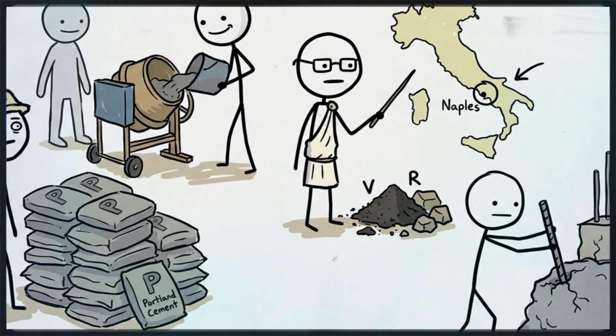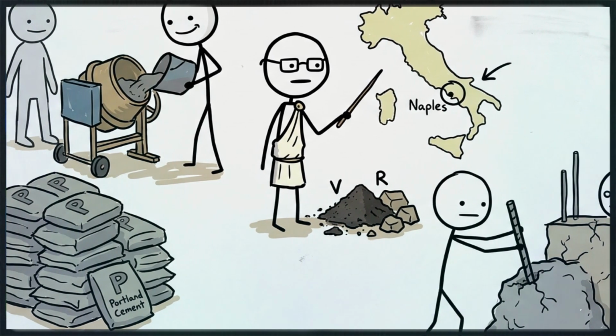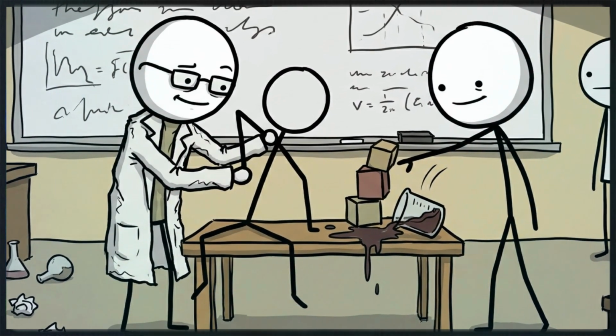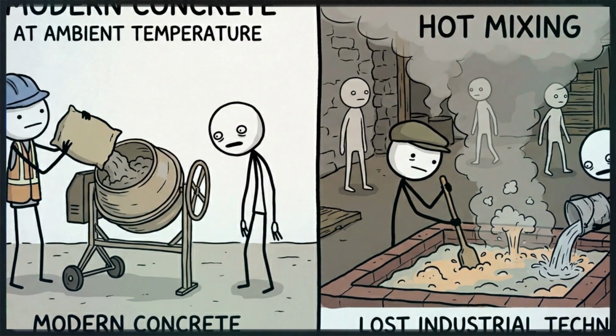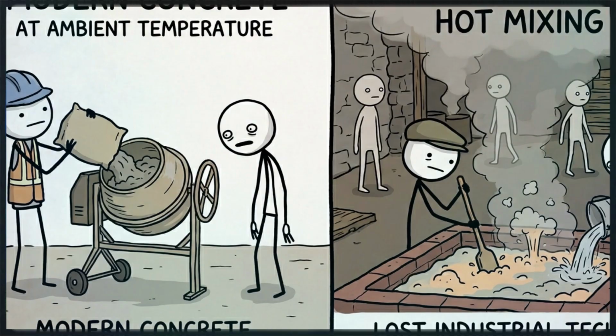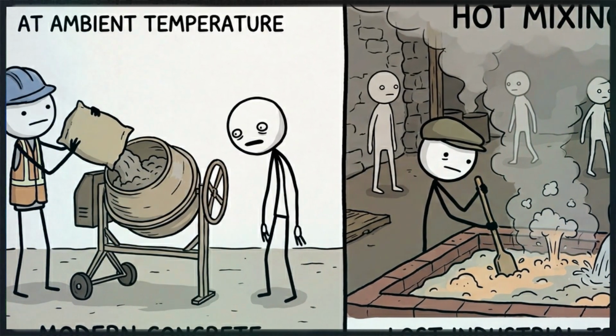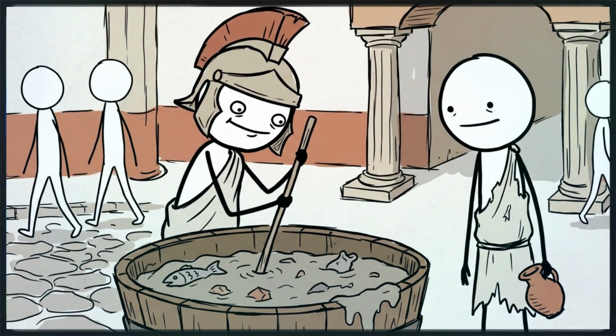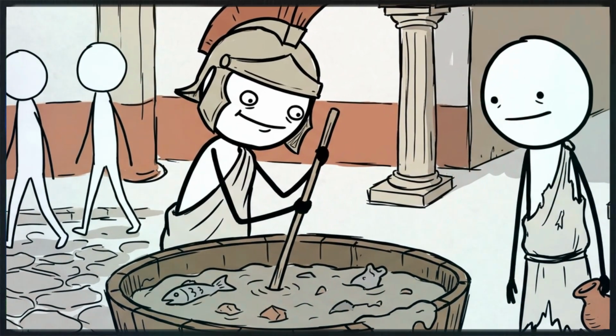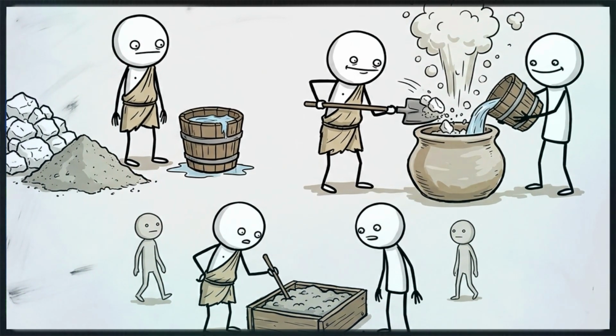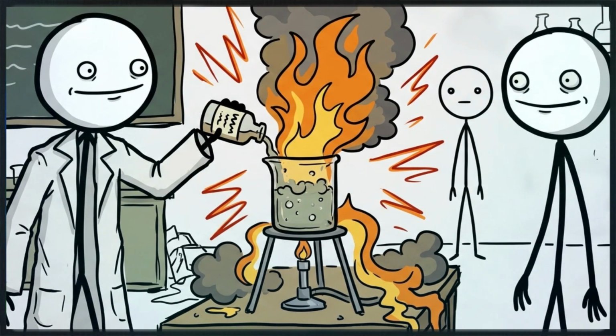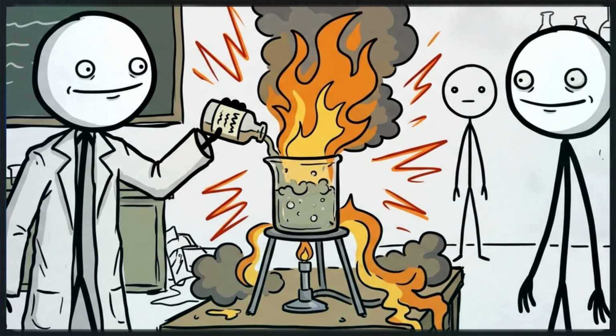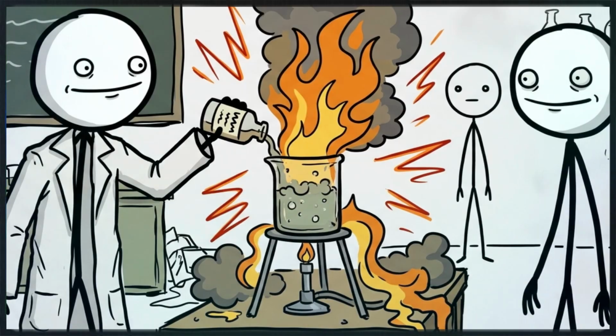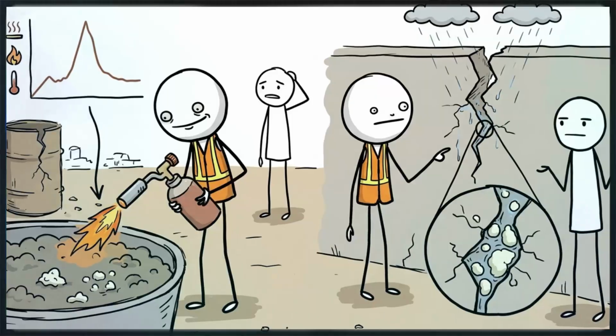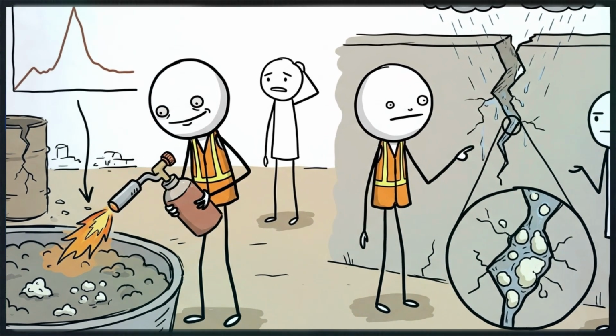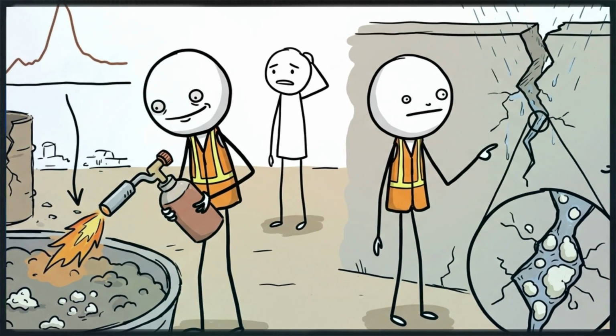So, if we understand the chemical mechanism, why can't modern civil engineering immediately replace Portland cement with Roman concrete? The barrier to replication lies in thermodynamics, specifically a lost industrial technique known as hot mixing. Modern concrete is made by mixing slaked lime, calcium hydroxide, with water and aggregates at ambient temperatures. Material physicists have determined that the Romans did something terrifyingly different. They mixed raw, highly reactive quicklime, calcium oxide, directly with the volcanic ash and water. This triggered a violent exothermic reaction, driving the internal temperature of the mixture up to 80 degrees Celsius, 176 degrees Fahrenheit. It was precisely this extreme, localized heat curve that allowed the unique lime clasts to form and establish the specific chemical environment required for the self-healing properties to activate.